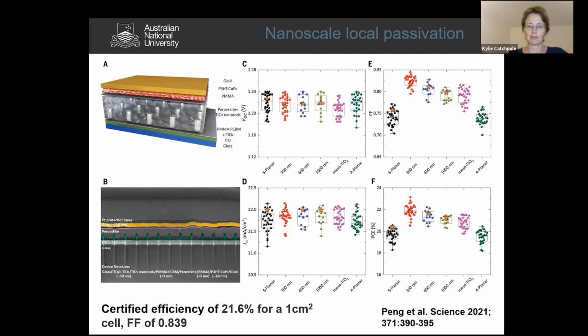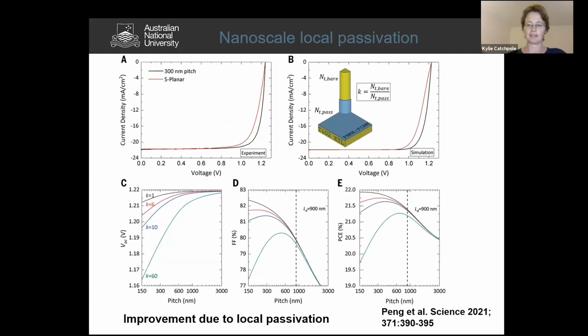So in order to understand what was happening in this device, what we did was to do some 3D numerical modeling, and the structure is shown in the top right there. So this is an element of the cell showing the nanorod, and we modeled the nanorod as partially covered by a passivation layer. So about 30% of it is uncovered and the rest is passivated. And then we can vary the pitch there, so that's the spacing between the nanorods.